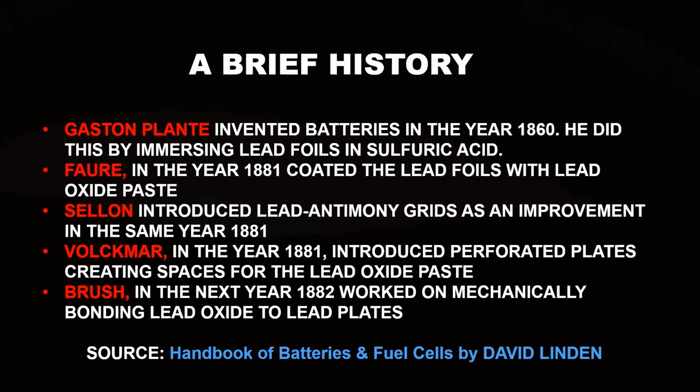In the same year, Sellon introduced lead antimony grids. Instead of very soft lead foils, the lead antimony grids were a bit harder because antimony imparts hardness to lead. In 1881, Volkmar introduced perforated plates, creating space for the lead oxide paste. And in the very next year, that is in 1882, Brush worked on mechanically bonding lead oxide to lead plates.